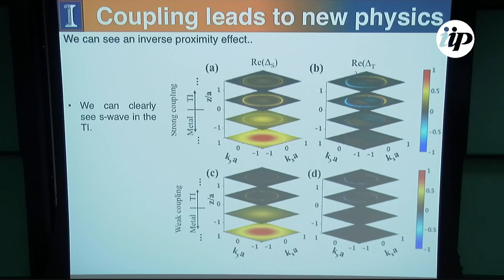And it turns out that in order to be able to get the topology, in this case, since it's time reversal invariance, we have spin orbit coupling that actually starts bleeding into the superconductor. So you can see this is the superconductor, and this is the P wave, and you can see that for very strong coupling, you can see clear signatures of the topology within the superconductor, whereas within the weak coupling regime, you see almost nothing.